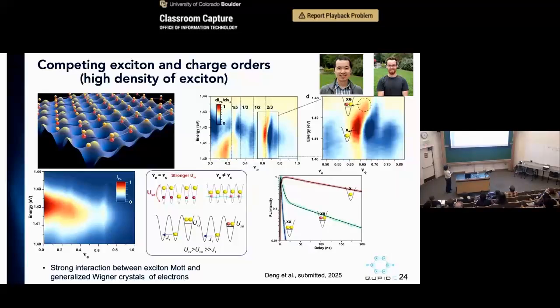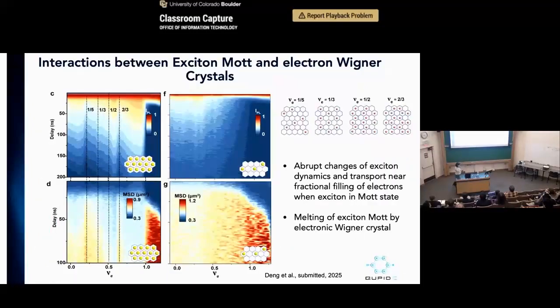Then we can look at the dynamics of all these different species. Again, the single excitons decay very slowly. If you have 2 excitons, as I discussed, it already decays faster. If you have an exciton and a charge, it's somewhere in the middle: slower than 2 excitons, but still faster than the single excitons. And now what we wanted to look at is how the exciton transport is going to change with these charge orders. So we look at 2 cases.